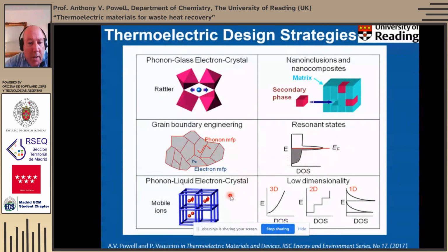A type of material that I will speak about quite a lot, because we've been doing a fair amount of work on this over the last few years, is what's called a phonon liquid electron crystal. And this is a material where we have some sort of underlying lattice with mobile cations usually within that lattice. And at some critical temperature, those cations, effectively that sublattice, either melts or partially melts, and that then could lead to significant reductions in thermal conductivity.